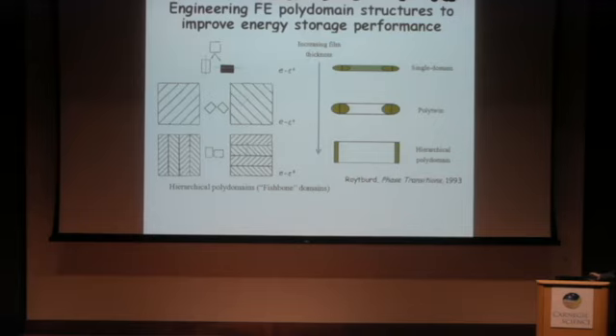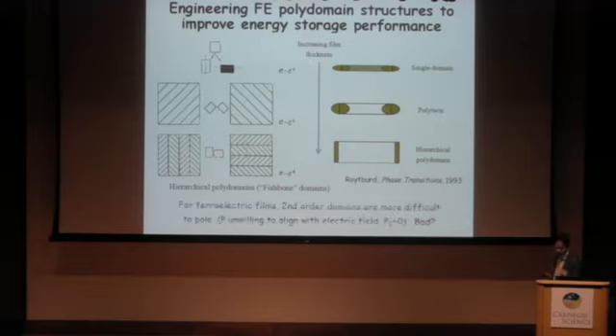I believe a lot of earlier presenters already showed nice pictures of this second-order or higher-order polydomain structure. So you're basically trading off the residual elastic strain energy: you're reducing the elastic strain energy at the cost of extra energy associated with creating extra interfaces. These second-order or higher-order polydomain films seem not very useful for memory applications, because the domains are usually aligned with polarization head to tail. The remnant polarization is likely to be close to 0, and the overall apparent polarization is unwilling to align with the electric field because of the interaction between the domains. So this is good for one type of technology, but maybe not another. For dielectric capacitors, this could be an ideal candidate.